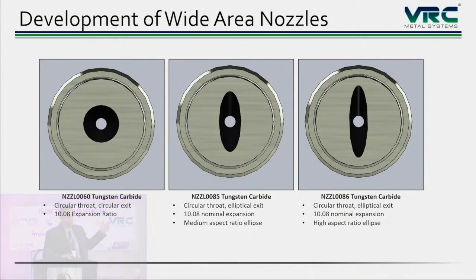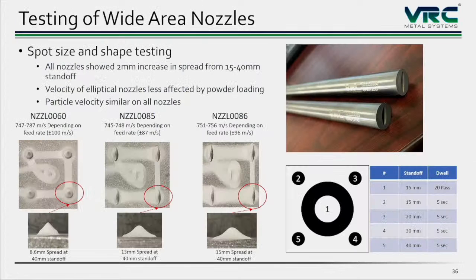So we're looking at a couple different geometries. The first is, well, they're both an oval or an ellipse exit, but using a standard circular throat. And what we did was we took our nozzle 60, which is here, and we took the expansion ratio we had on nozzle 60, which works very well for a lot of these nitrogen sprays, and we opened up the exit to an ellipse, but maintaining the same expansion ratio, all right? And we got two different ellipse shapes here. So let's look at the performance.